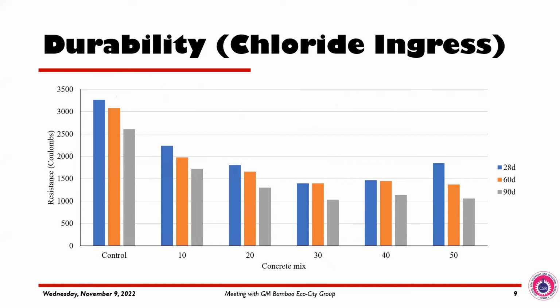I did a little bit of durability tests. One of the common durability tests is to look at the chloride ingress. Mostly durability has got to do with the pores within the material. So if you can look at how the pores are arranged and how easily some ions can flow through the material, then you can understand the durability. So I used the rapid chloride permeability test, and then I prepared this concrete. And of course, you realize that almost all the materials containing clay pozzolana had a lower ingress of chloride compared to the control.